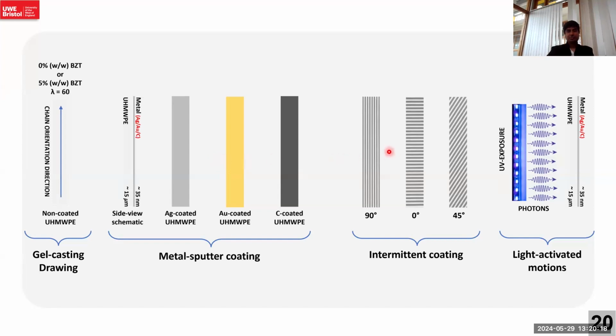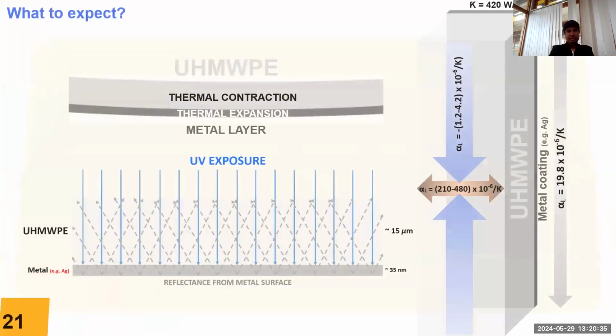And we also devised some patterns within the film so that we can generate different mechanical deformations like bending and twisting using different patterns of the coated films. So what we were expecting, if we create a metallic layer on the back end of the film, is this: the oriented polyethylene has a property of thermal contraction. That means when the heat is there, the polymer chains tend to contract. But the metal coating has a positive coefficient of thermal expansion. So upon heating, they will actually expand.